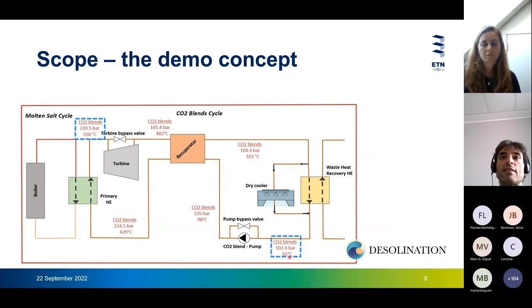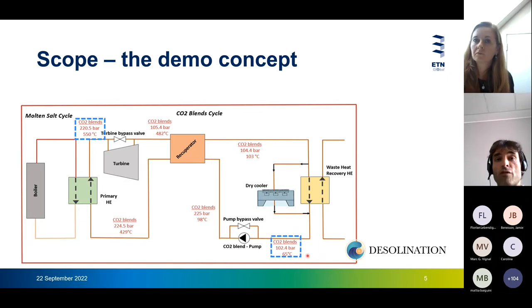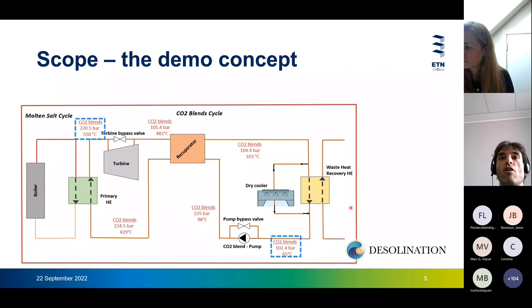The minimum temperature is set by the desalination part. So in this particular case, we are operating with quite a high minimum operating temperature in the range of 65 degrees C. As you can see from this picture, we have 2 different systems to reject the condensing heat. One is a dry cooler to decouple the power cycle from the desalination part, just in case something is not working, but also because the waste heat recovery heat exchanger is designed for the desalination part, which is significantly smaller.